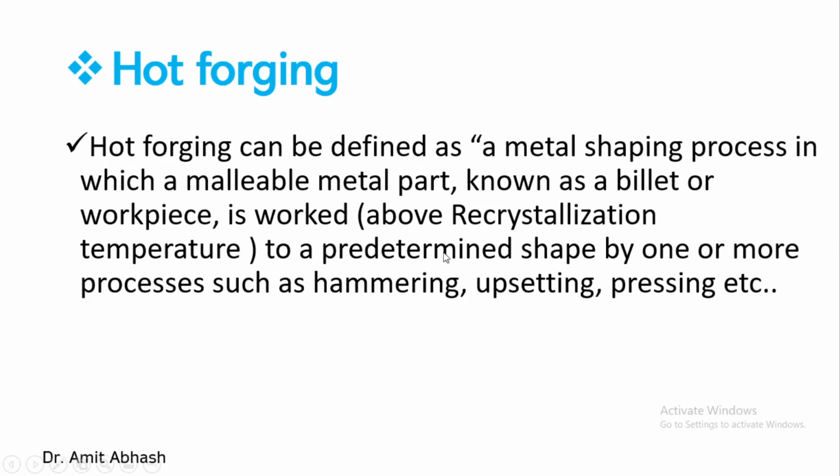Saying just above the recrystallization temperature doesn't have a proper meaning. I should say here 50 to 100 degrees above the recrystallization temperature. I think you should add it here: 50 to 100 degrees above the recrystallization temperature, to a predetermined shape by one or more processes, such as hammering, upsetting, or pressing, or whichever type of forging you are choosing, to get the desired shape of the final product.